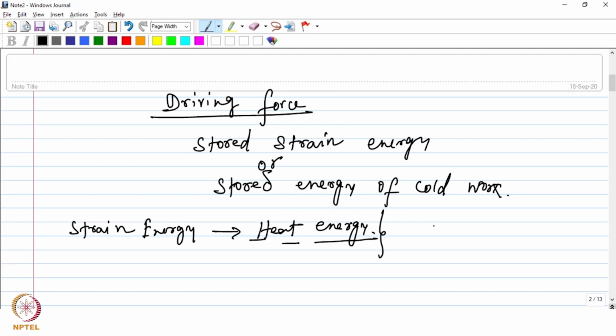One such instrument is DSC, or differential scanning calorimetry, which basically measures the heat flow, right? So from this, you get to know different kinds of phenomena that can occur in a material when you heat it, right? So that phenomenon can also be the release of the strain energy. Okay. So when the strain energy is released, as I said, this will be released in the form of heat. And since this particular technique measures the heat flow, it will show you a peak corresponding to the temperature at which the strain energy will be released, right? Because that will increase the heat flow and it will be captured by the instrument.